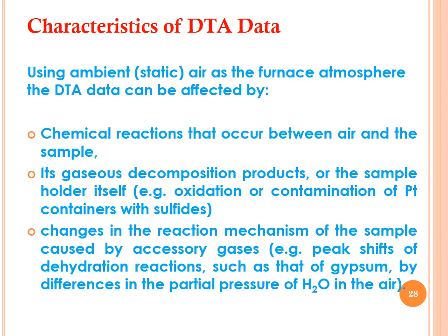Other causes are its gaseous decomposition products, the sample holder itself, its oxidation, or contamination of the platinum container with sulfides. Platinum sulfide may be formed. Changes in the reaction mechanism of the sample are also caused by accessory gases, that is, the peak shift of dehydration reactions such as that of gypsum, by differences in the partial pressure of water in the air.